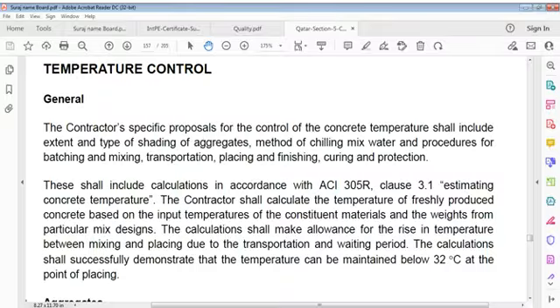Contractor shall calculate temperature of freshly produced concrete based on input temperature of constituent materials and weights from particular mix design. Calculations shall make allowance for rise in temperature between mixing and placing due to transportation and waiting period. Calculations shall successfully demonstrate that temperature can be maintained below 32 degrees Celsius at point of placing.